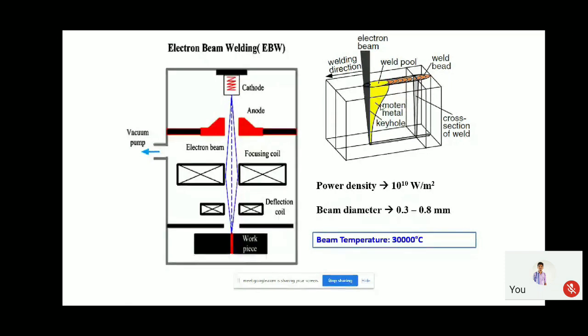From the industry point of view, it is widely used for titanium alloys, because titanium is not possible to weld with the TIG welding process because of oxidation issues. You will get cracking, porosities, everything. And the investment cost of electron beam welding is very, very high. Even for a 40 to 50 mm thick plate, you need to invest more than 8 crores for a single machine, and the maintenance cost is very high. So very rarely do people working in the aero industries have this electron beam welding facility.